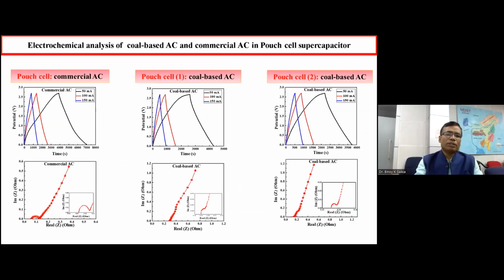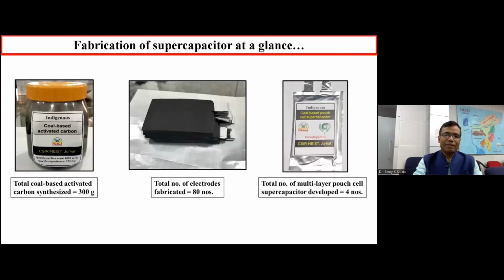And then we made a pouch cell, because we have to go to the application field, as I told you. After getting the materials, we made a supercapacitor pouch cell of the coal-derived carbon. Then we compared with the commercial one, and we found that yes, this is also comparable. You can see in the results the surge response and also the resistance properties in the Nyquist plot. You can see considerably similar, or even better, parameters in the pouch cell too, which is very suitable for utilizing particularly in the energy test bed.